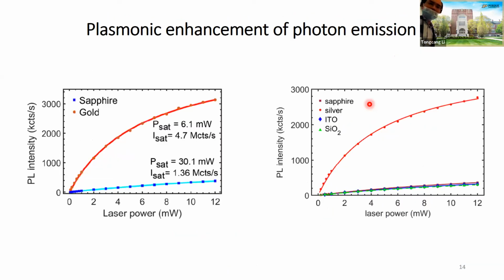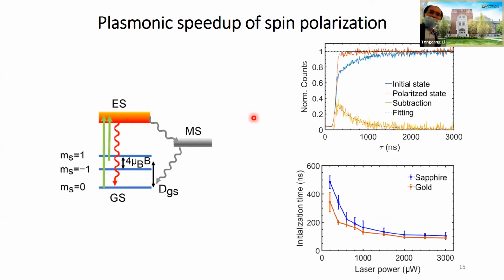And then we also studied different materials. For example, we compared sapphire, gold, silver, ITO, and silicon oxide. Silicon dioxide, ITO and sapphire do not have plasmon enhancement. Only silver and gold have. That also confirms this is plasmon. And then the plasmon enhances the spin polarization a little bit, not too much. We compared silver and gold, and the difference is maybe a factor of 1.5 or so. But the main problem is that for this one, the optical decay is just a small percentage of the overall decay. That's why it's very dark.